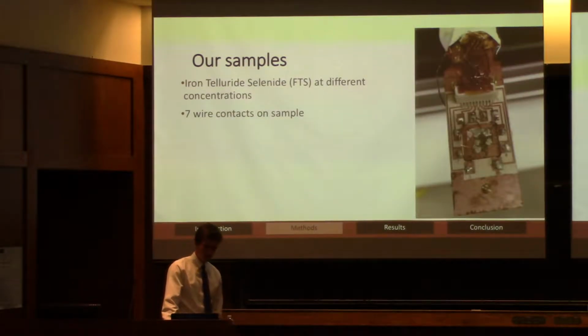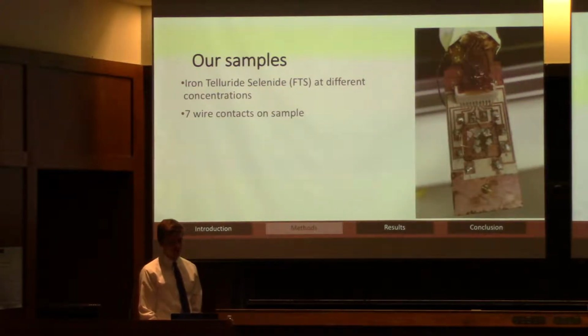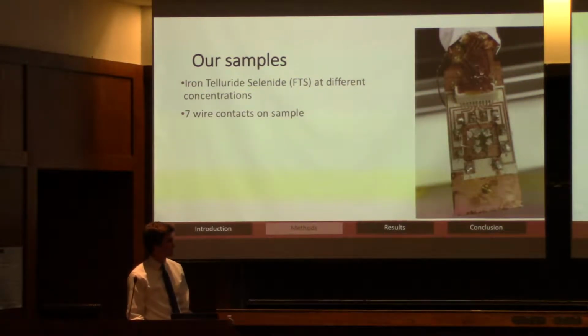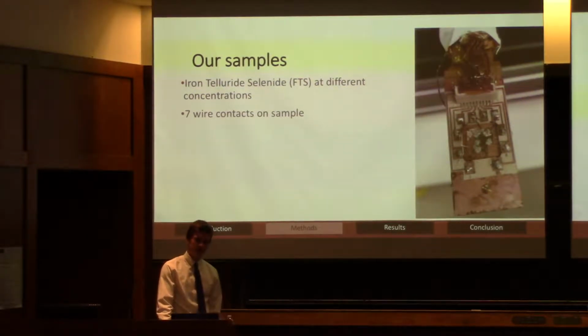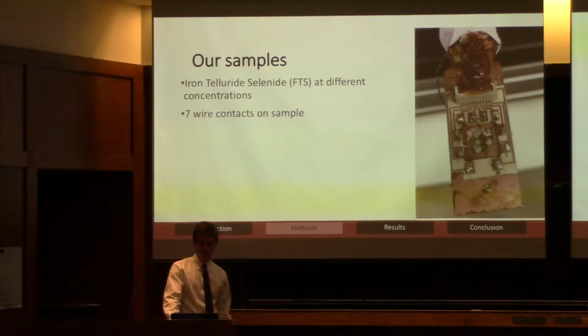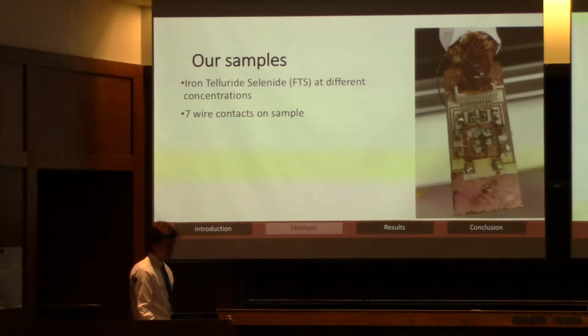So again, working with iron telluride selenide, we have different concentrations of that. The most interesting one so far has been half doped, so almost equal amounts of tellurium and selenium in here, and that's a picture of that device. The reason we work with iron telluride selenide is there's evidence that this sample will show this new phase of matter. And we put this on a device like this, we attach those wires, and in a perfect world, you get 7 clean contacts. Sometimes that doesn't happen, but that's the goal. And then we test this for that new phase of matter.